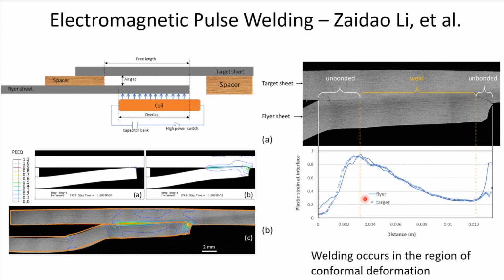So we realize that if you look at the bonded region, within the bonded region, not only is the amount of plastic strain high, but also the value of the plastic strain on either counterpart is almost the same. And that's what is normally regarded as conformal deformation. So besides needing a high amount of deformation, you need conformal deformation. That's an additional criterion for bonding, at least as far as EMPT is concerned.